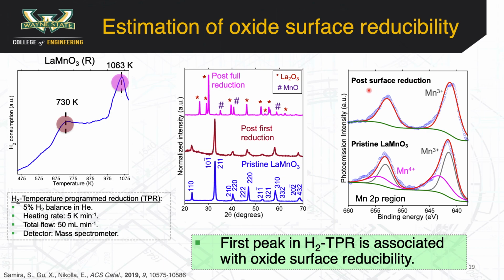Combining these bulk studies with some surface characterization tools such as X-ray photoelectron spectroscopy, what is observed is pristine LaMnO3 has a combination of both Mn3+ and Mn4+ in the near surface region, while post surface reduction after the first peak, the Mn4+ represented in the pink curve here is shown to be absent, thus suggesting that the surface is reduced. Therefore, the temperature at which the first peak occurs is associated with the oxide surface reducibility.